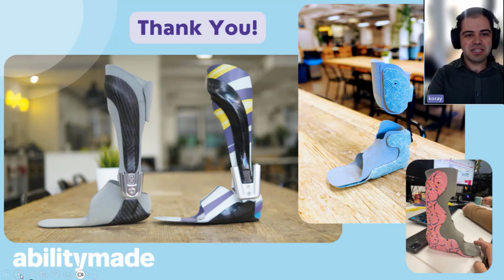So it's easy to adjust, to heat out and to grind. And also an added benefit is that if you need to, it's great with growth and changes in fit, so you don't need to replace the whole entire carbon shell and joint. Instead, you can just replace the TPU or the nylon part. So things like flexible toe plates.